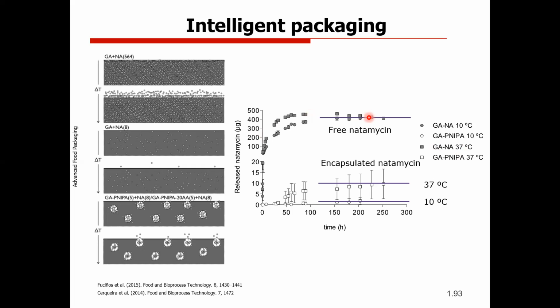And then we compare the encapsulated natamycin at 37 and 10 degrees. And you can see here that if you compare 10 with 37, at 10 the release is very slow and a small amount is released. But when you go to 37, we have a very big release of this active compound. So the nanogel is giving a response to the temperature and is releasing the compound. So we show with this work that it's possible to have this kind of system, a packaging that only releases if there is a temperature abuse.